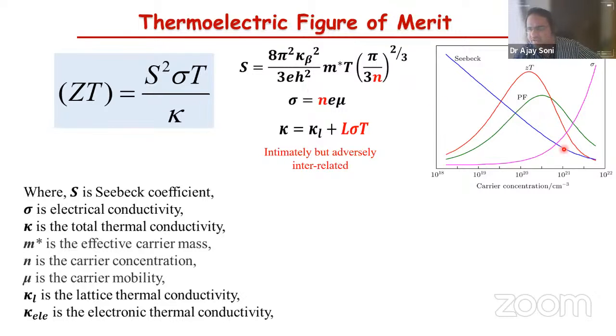So in that context, you can think about it. If you look at the number of charge carriers in the material, if you go to 10 to the power 22, which is the metallic region, these are metals like silver, copper, gold, nickel, iron. These materials have a large number of charge carriers. They have a good electrical conductivity, but because the number of charge carriers is large, the thermoelectric power is poor. So metals are not good for thermoelectric research.